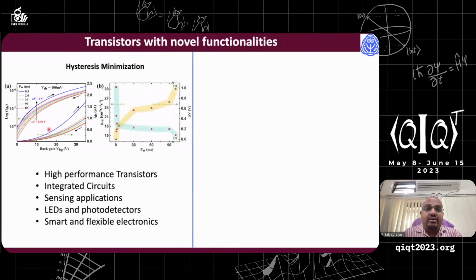So for that, if you use a pulse voltage, we have demonstrated that you can completely remove this hysteresis. But this is as far as the hysteresis minimum is concerned, which is required for high performance transistors, integrated circuits, sensing applications, LED and optoelectronics and smart electronics, because you need stability in the threshold voltage.